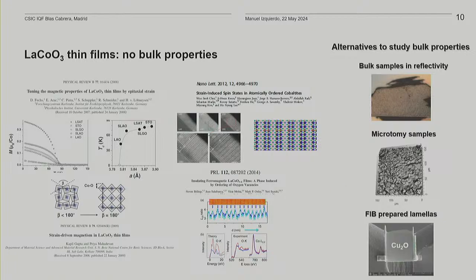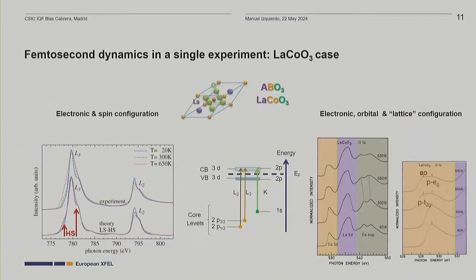I'm going to discuss the first 2 cases. So the technique of use was, or what we thought was possible, was to use X-ray absorption spectroscopy, and then you can do studies both at the cobalt L-edge and at the oxygen K-edge. And so the cobalt L-edge gives you information on the electronic and spin configuration, and the oxygen K-edge gives you much